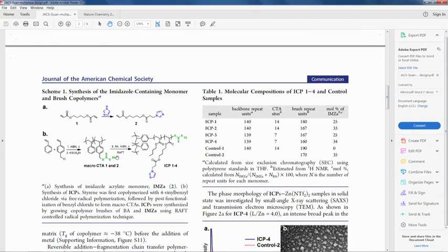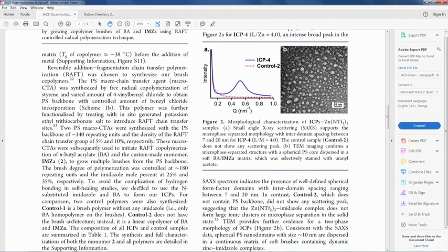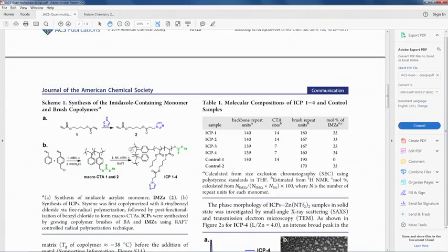After that, in the second step you can put in N-butyl acrylate. This is the RAFT reaction, and since this is coming out of the side chain, you create a brush of N-butyl acrylate from this unit. In this N-butyl acrylate that you are taking, you mix not only N-butyl acrylate, along with that you mix another monomer of this variety.